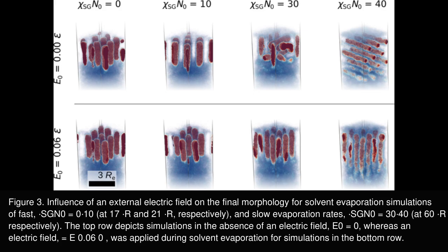The authors interpret these results as demonstrating the critical role of electric fields in controlling domain orientation by competing with solvent density gradients and surface enrichment effects. Thus, the electric field extends the processing conditions that yield desired perpendicular cylinder orientation during dynamic solvent evaporation. This work thus illustrates how the interplay between evaporation kinetics and electric field strength governs the self-assembled nanostructure in thin copolymer films.